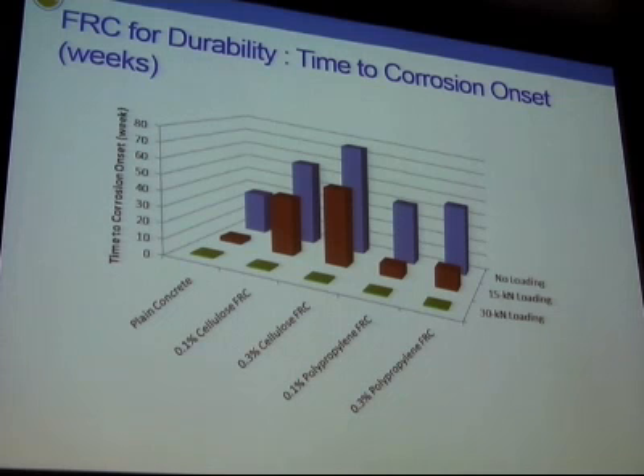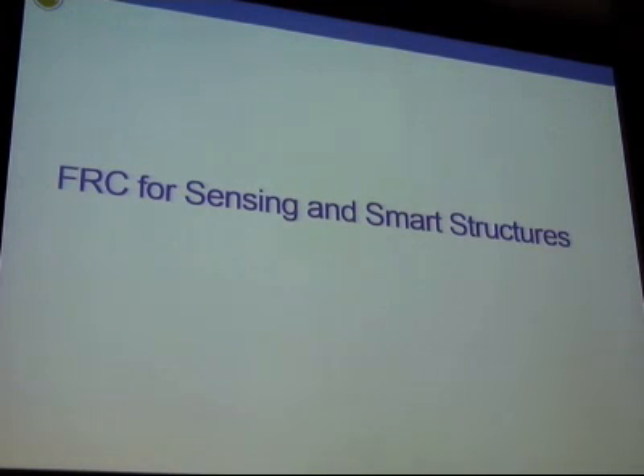So fiber-reinforced concrete being a very durable material, because of its crack control capacity, you can actually get a lot more years out of a structure as a result of fiber use. And also for the repair side as well. If you're repairing these structures with fiber-reinforced concrete, one can easily predict that you would get a lot more life out of the structure by using fiber-reinforced concrete. So that brings me to the last topic.